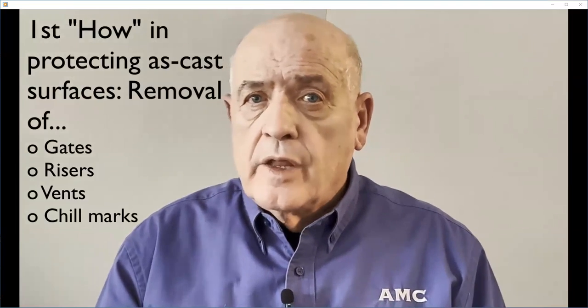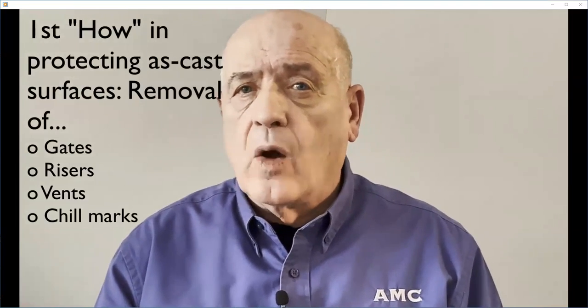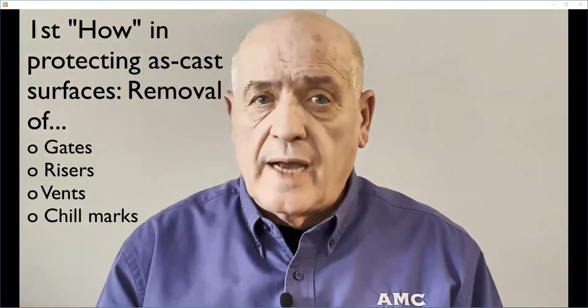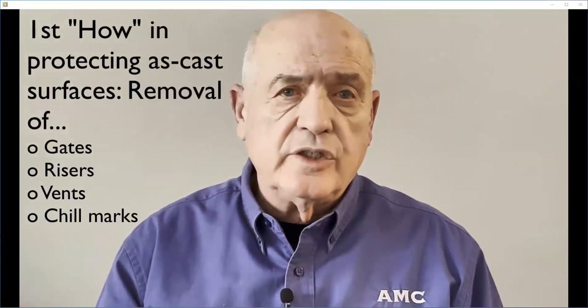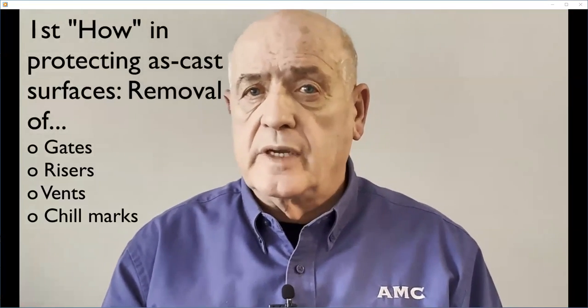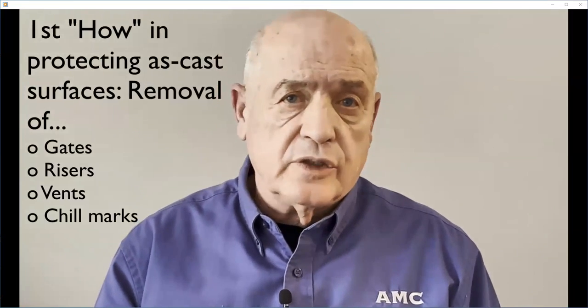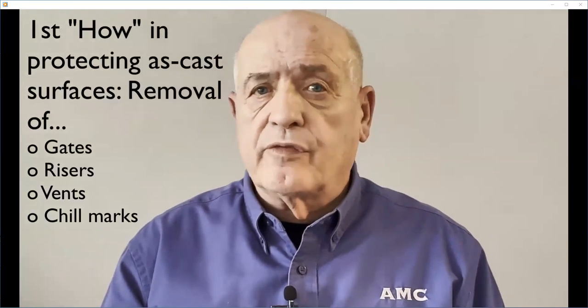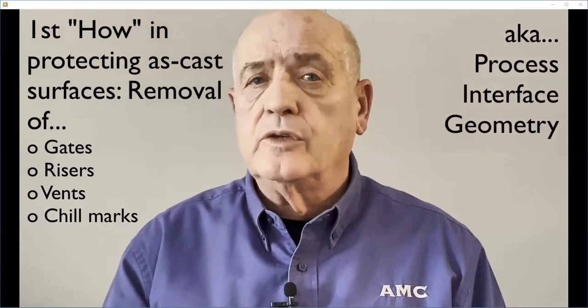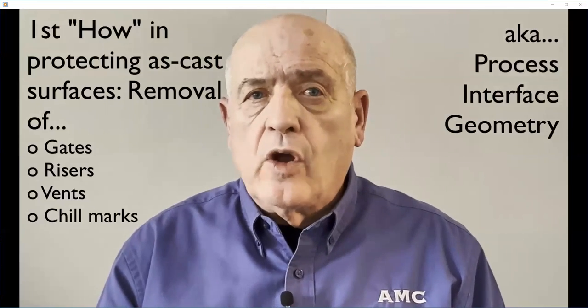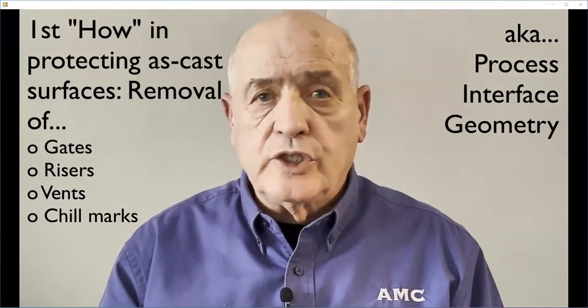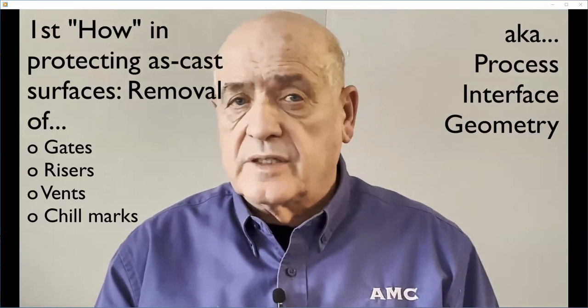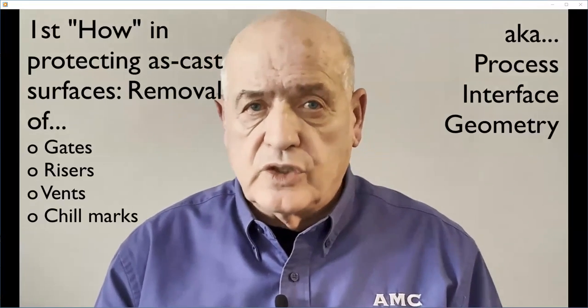Now let's address how finishing is done for complex high specification castings to protect their as-cast surfaces. The first finishing process is to remove the gating system, the risers, and the vents, which are the additions to the casting's design geometry to fill the mold, feed solidification shrinkage, and remove gases in front of the liquid metal as it flows into the mold. For short, we call those geometries plus metal chills in the mold walls of sand castings process interface geometry.